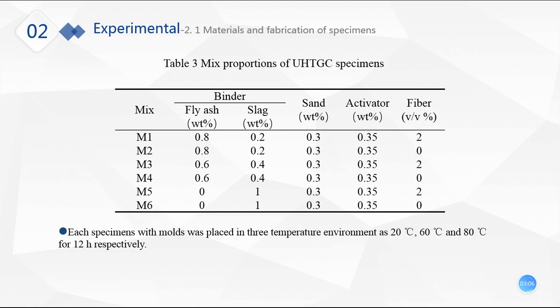6 mixes of geopolymer and geopolymer-based composites were prepared. That's the mixed proportion, from M1 to M6. Among them, M1, M3, and M5 are the specimens reinforced by fiber with 2%. Each specimen with molds was placed in 3 temperature environments, 20, 60, and 80 centigrade, for 12 hours respectively.